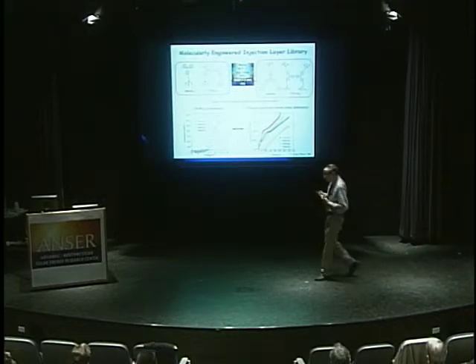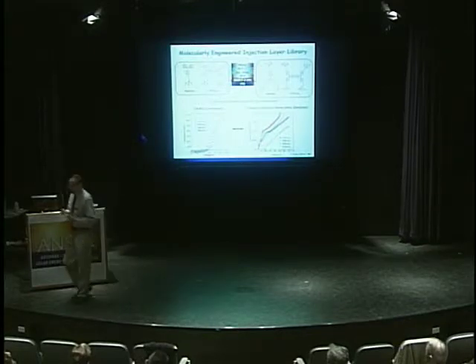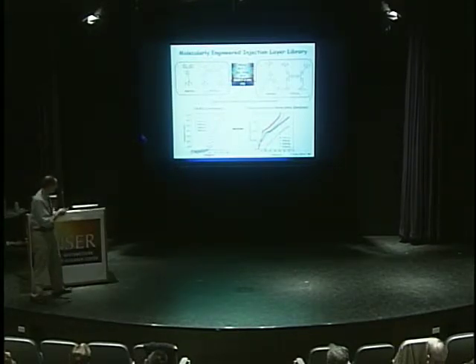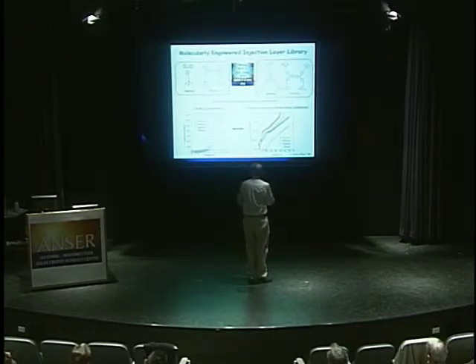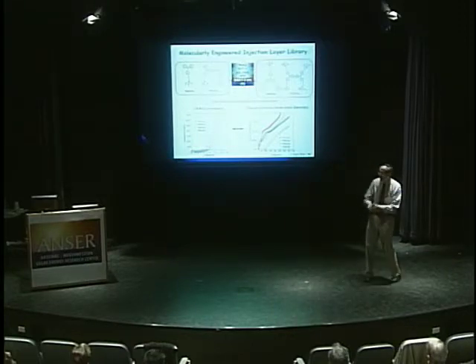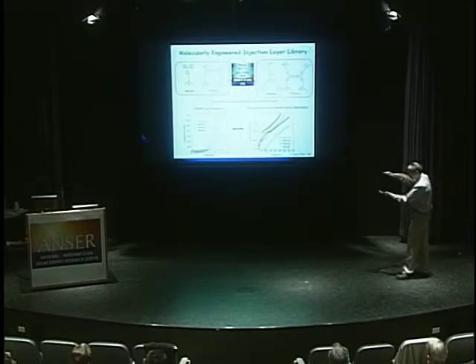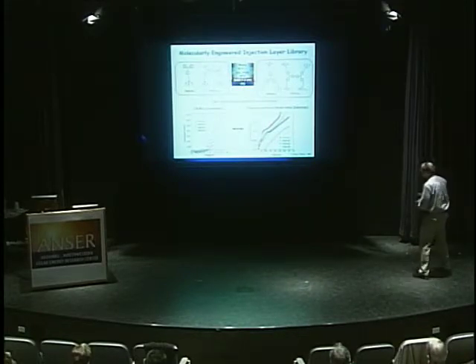And of course, when they're on the surface, we characterize them by everything from cyclic voltammetry to X-ray reflectivity at the Argonne synchrotron. What you see, which is most intriguing, is this is the material I talked about so far. This material, which has 4 legs, which places the pi system of the TPD right up against the ITO band structure, whatever that may be, has a much greater current density, and the OLED has a much greater luminance.